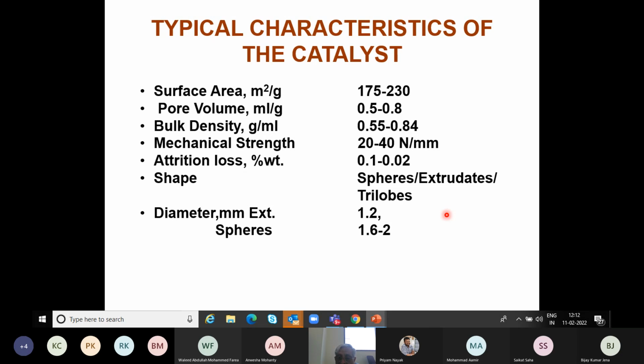We need, of course, good mechanical strength, because a typical reactor could be something like 10 meters tall. And so the catalyst at the bottom sees the full head of the catalyst sitting above it. The bottom part of the catalyst should not get crushed to a powder, otherwise it will increase the pressure drop across the reactor. So mechanical strength and attrition index are the two very important variables in terms of the hardness of the catalyst. There are two types of shapes that we produce. It is either spheres or extrudates.